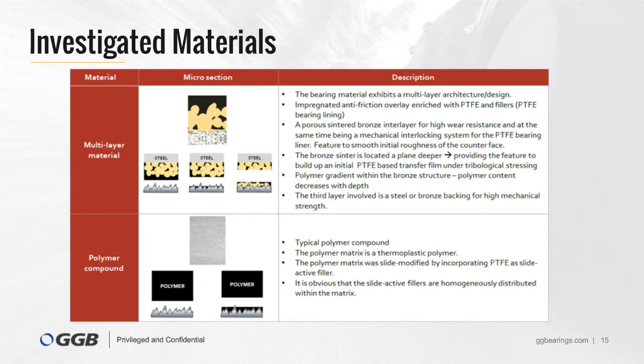One important feature of this material is that it generates a protective transfer film on the counterface, which then protects the bearing material from further damage by the counterface. The second material we investigated is a typical polymer compound.